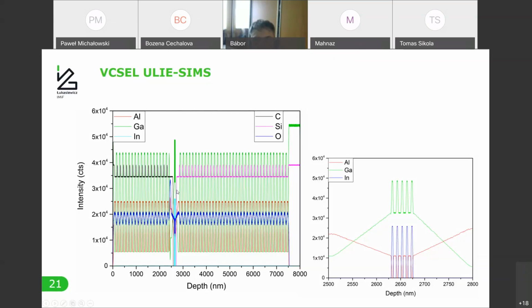Whereas the polishing itself worked a little bit differently, because I used relatively high energy, that was 2.5 kV. But this was with an extreme incident angle that was well above 70 degrees. And I also applied some additional voltage to the sample. So these ions could not actually hit the surface of the sample. They were just sliding at the very top, just above the surface of the sample. So whenever they reached some leftover contaminant, they polish it and remove it. So the polishing was used with much higher energy, but with this additional voltage to prevent the sputtering of the surface. So this was just for making the surface very flat. And then I just use it for a few seconds every half an hour or something like this.